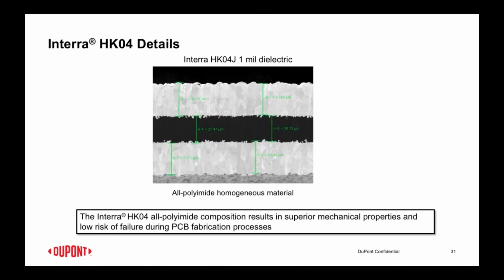And again, this is a cross section of it. This is the 1 mil material. This is the J material. You can see that the copper profile that we use is relatively low. Again, we don't want to have any high pot failures or shorting between the layers. As we go to thinner dielectrics, we can also further decrease the copper profile to make sure that we meet all the objectives. And because it's a continuous film, it's a very strong material and very easy to process.